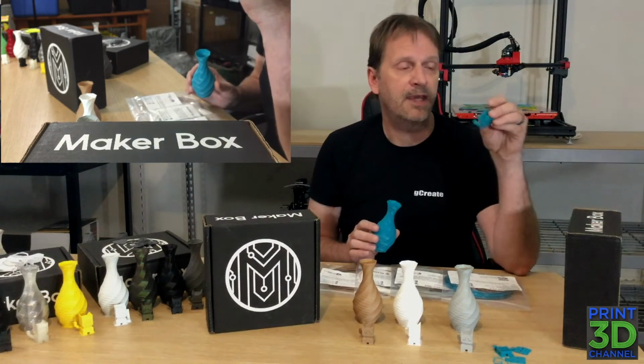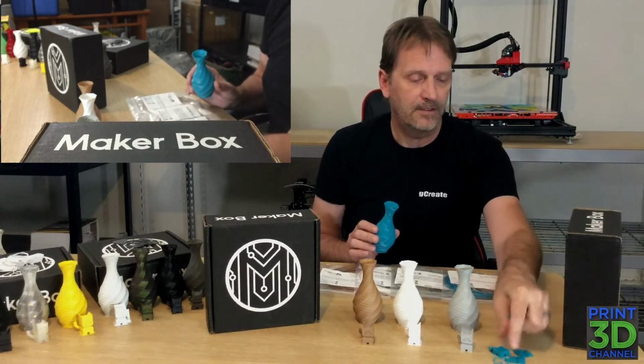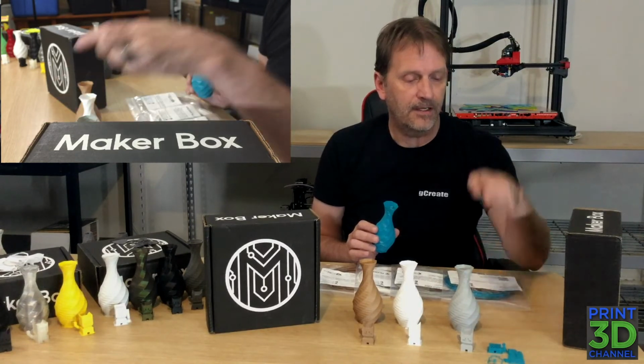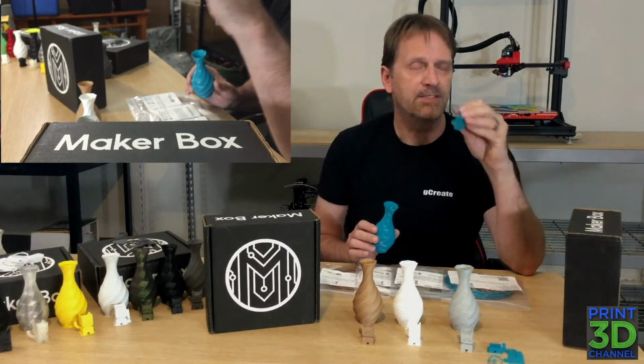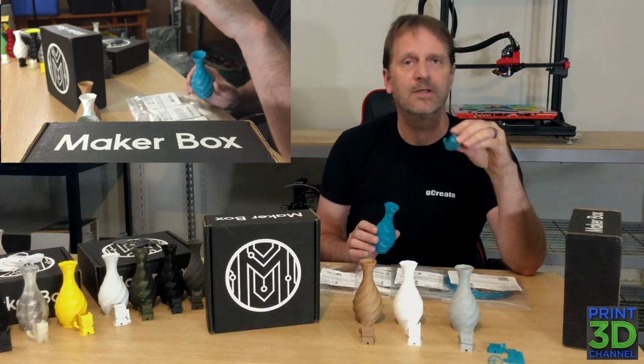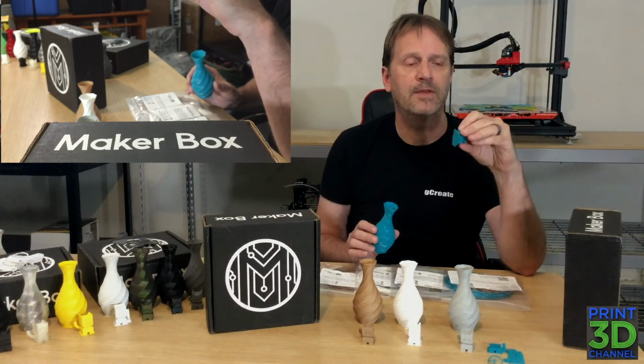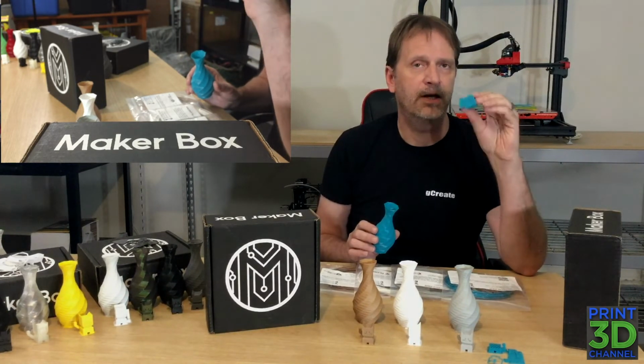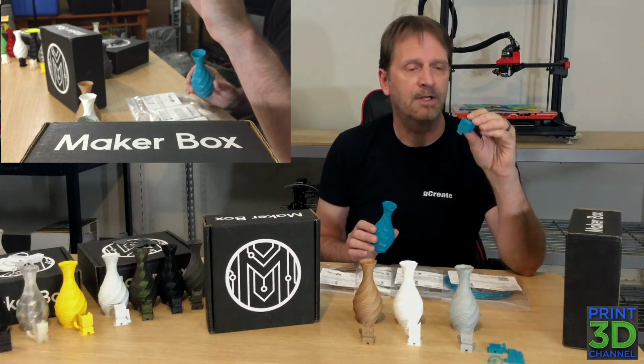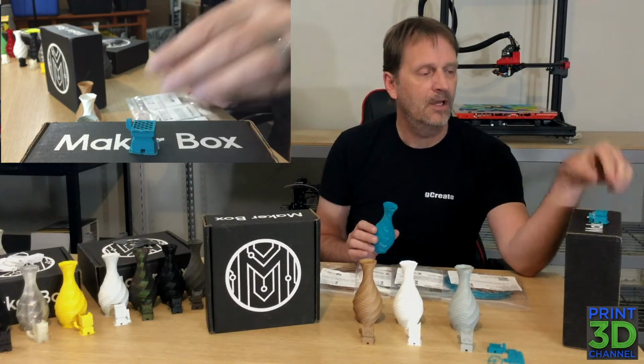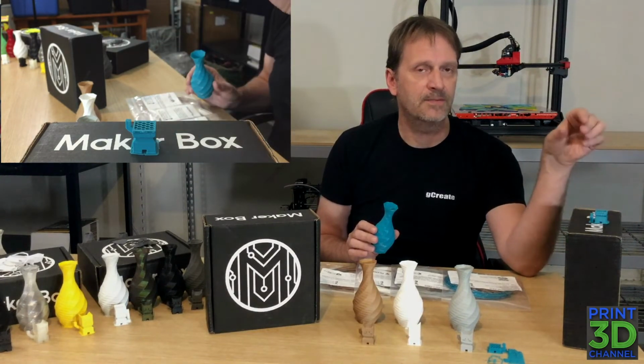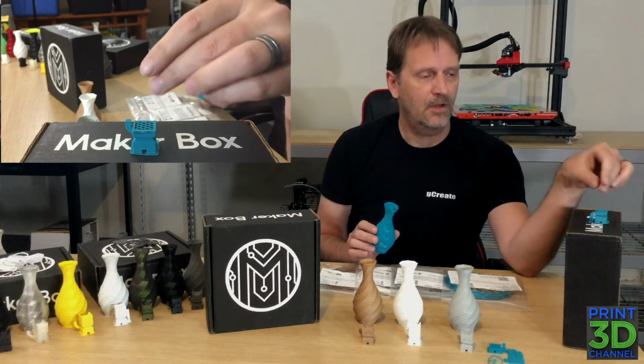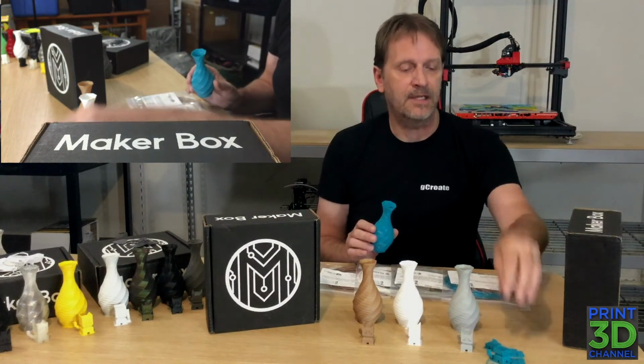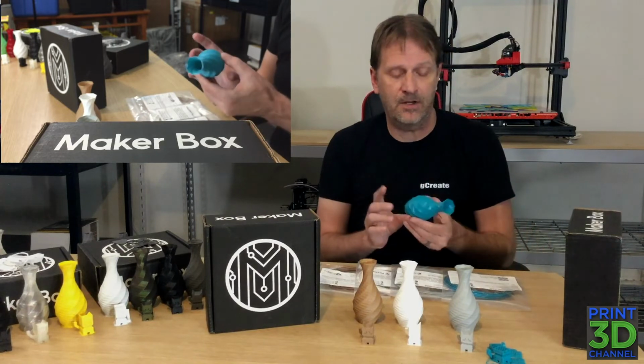But when we went to print the Cali Cat, and you can see I've got quite a few little fails sitting here, I found some diameter inconsistencies after I changed the temperature and the print speed and the bed temperature, a few things. I took the filament out and I measured it, and there were some serious diameter inconsistencies, which was causing some layer skips, and it was also causing some jams for whatever reason. So I stopped printing the Cali Cat because I didn't want to jam up the extruder and have to tear it all the way apart.